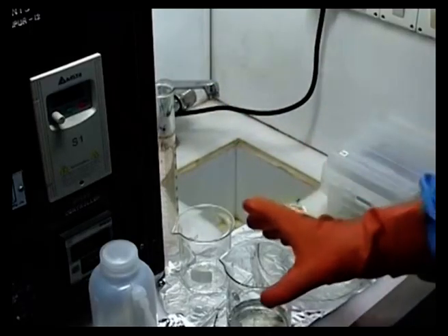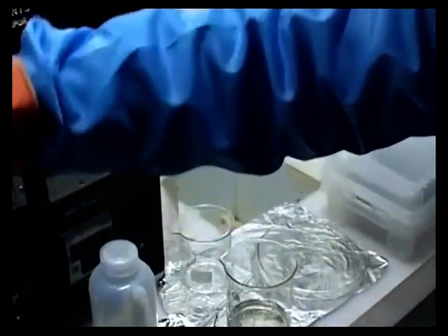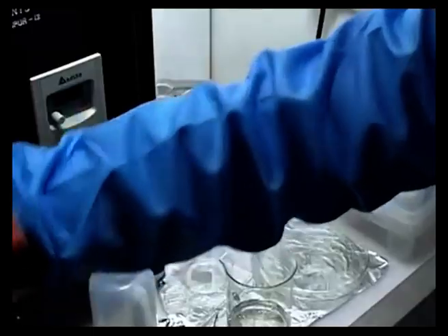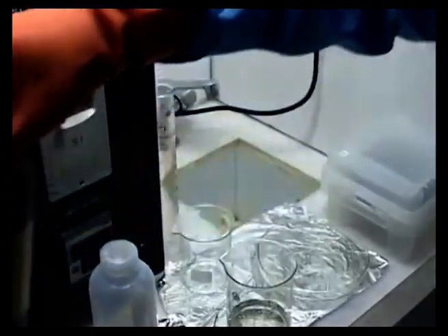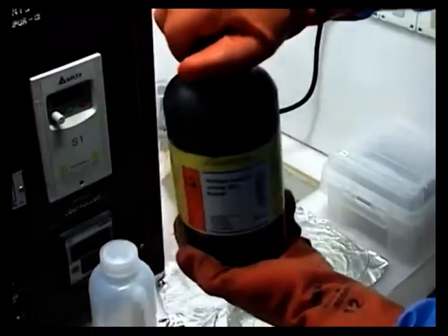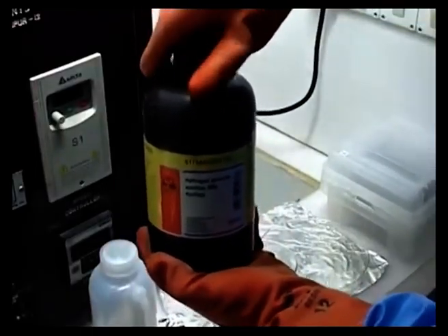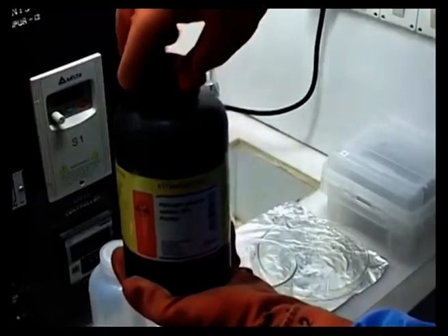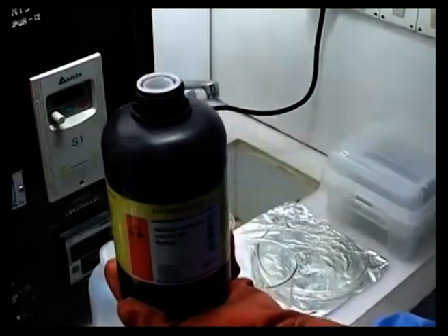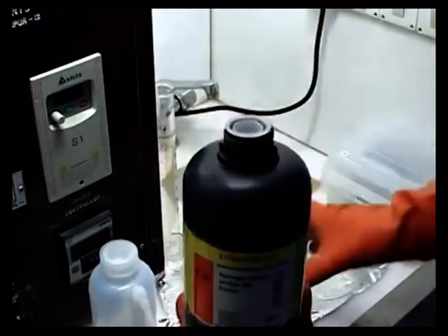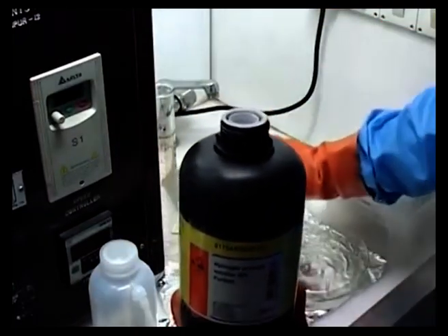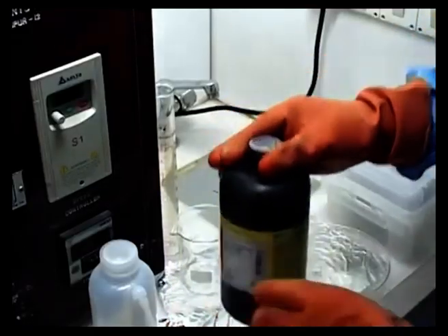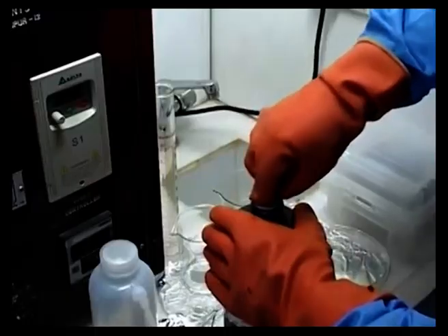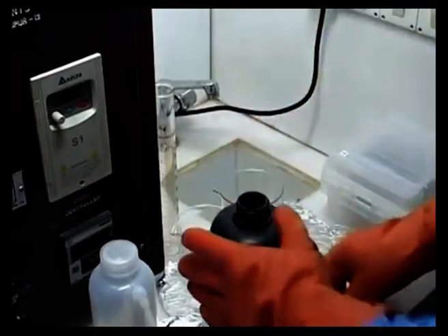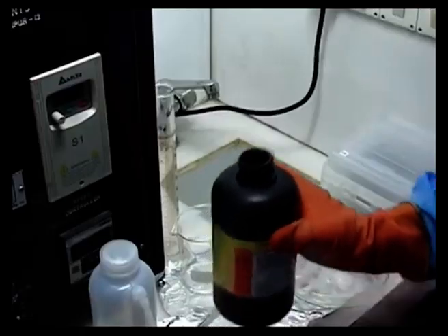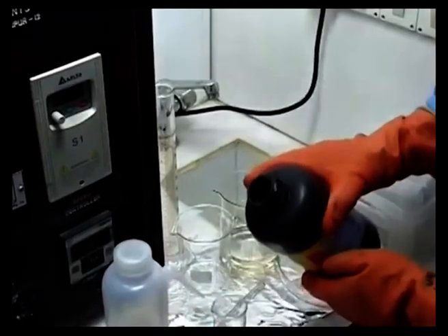Now we have to pour about 30 ml of hydrogen peroxide. So this right here is the container for H2O2, and the reaction is essentially an equilibrium reaction where a lot of hydrogen ions and hydroxides are generated, and essentially it's an equilibrium process which coats a layer of hydroxide onto the silicon dioxide, the nascent oxide surface, and also creates a lot of heat. Okay, so basically we need 30 ml of hydrogen peroxide. So we open this and pour exactly 30 ml of hydrogen peroxide into the secondary container here.